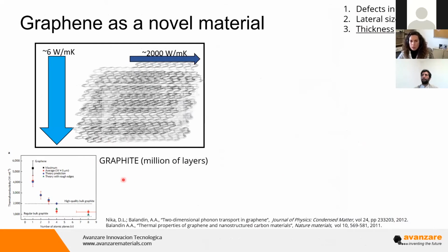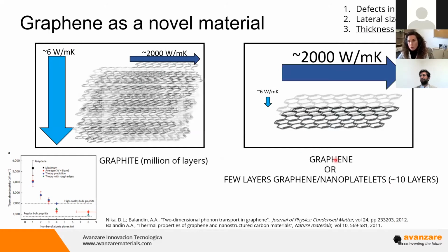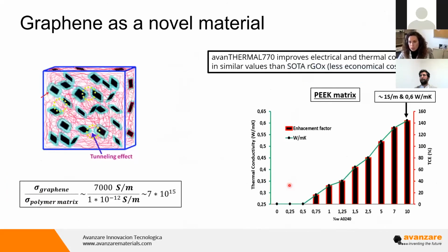If we take into account that graphite is also a good candidate to increase the thermal conductivity, because it also has an intrinsic high value of thermal conductivity, we need to understand that graphite is composed of millions of layers of graphene. So, of course, the contribution in the XY plane is high, around 2000, the same, but there is also an important contribution in the through-plane (Z) axis, which is about 6 watts per meter Kelvin. So in the case of graphite, this is reduced. And especially if we compare with graphene, the contribution in the XY plane is much higher than in the through-plane (Z) axis. Besides, in the case of graphene, there is a higher number of particles because it's an exfoliated material in comparison to graphite.